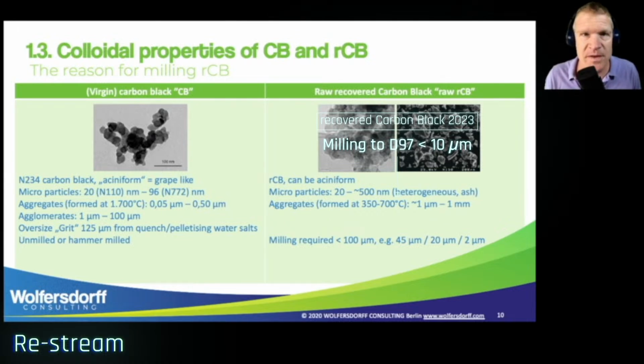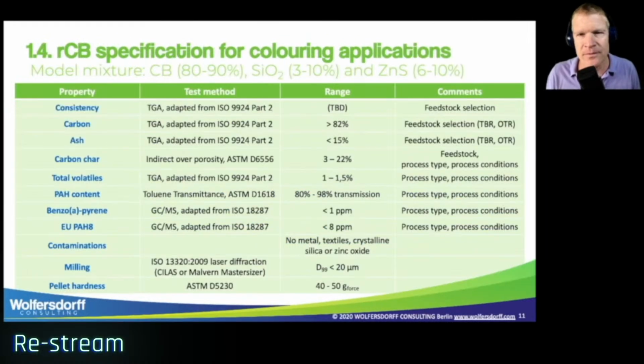We will get to the specification for coloring recovered carbon black in a moment. In some cases, actually, producers of recovered carbon black are milling to below 2 micron. This is the case for very low viscosity systems, for example, if you want to use recovered carbon black as color in paints or inks. So let's look at a specification for coloring applications.